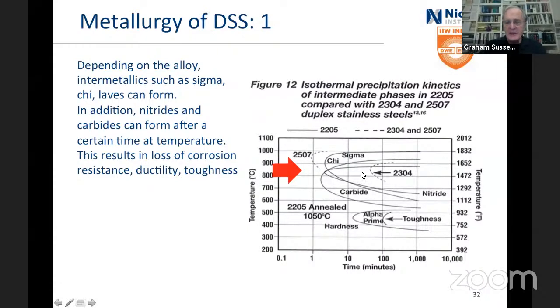So here's time at temperature from welding. So this is 1 minute, that's 0.1 of a minute. And here is a curve where the start of sigma phase happens in 2507. Here's the curve which we've got for sigma for 2205, there for 2304, and you can see quite clearly as the alloy goes down, the problem goes down. Nitride, I'll talk about that later.